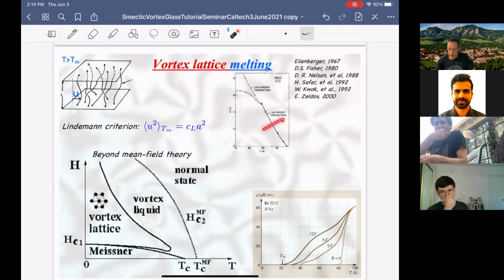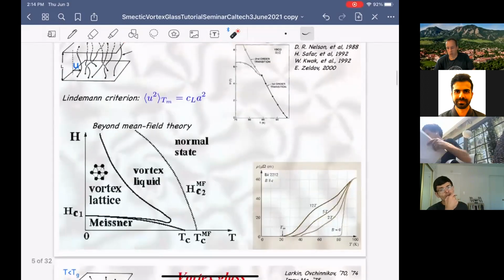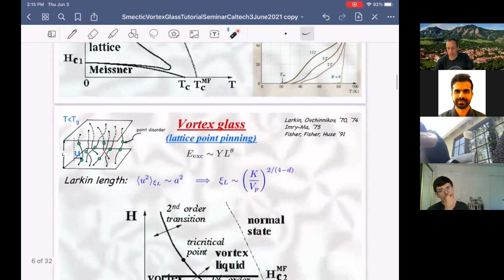And there's a lot of experimental data that sees this first order transition, and the most beautiful latest data was by Eli Zeldov, that actually showed thermodynamically that there's a first order transition across this melting line. So now this is the actual transition. It's a first order melting line, at least in the absence of disorder.